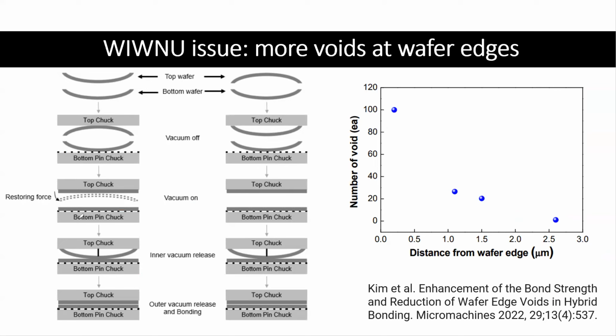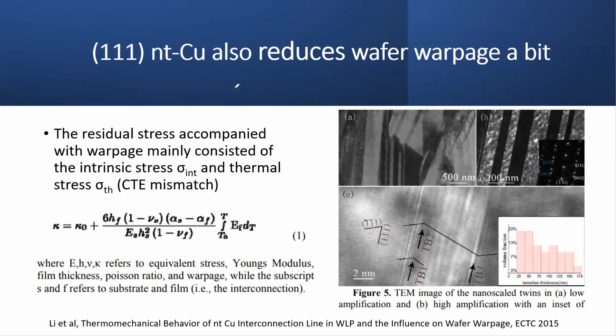They put material together and tried different shapes of die, either concave or convex, something like that, and they squeeze it and study the voids. They found that the voids at the wafer edges will increase. This is distance from the wafer edges. Okay, this is wafer to wafer. This is another experiment, right? They study wafer edges, which is a kind of warpage effect: at the edge of the wafer, you get the highest number of voids. It's because of stress, pretty much just stress. And then the nano twin copper can help solve that problem to some extent. They're probably not the only one to solve the problem, but they help, right?